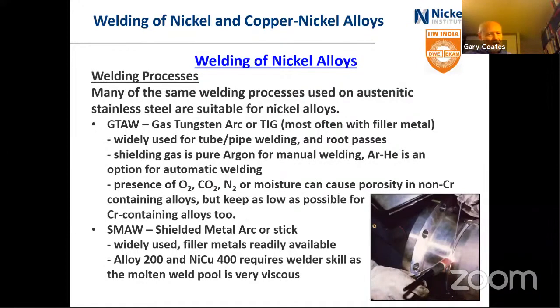The nickel alloy 200 and nickel copper alloy 400 do require welder skill, as the molten pool is very viscous. This is especially important in shielded metal arc welding versus, for example, TIG welding or even MIG welding. So you can't expect the welds to look as good as they do on, let's say, a stainless steel with stick welding. Still acceptable, but they're not as good appearance-wise.